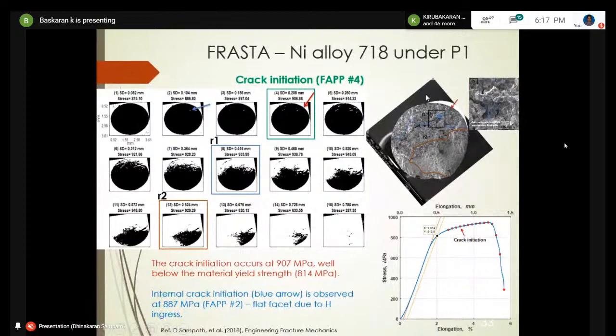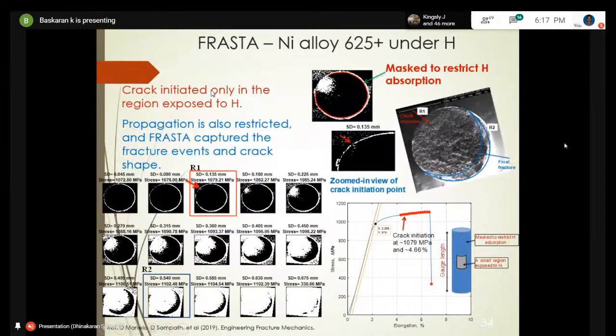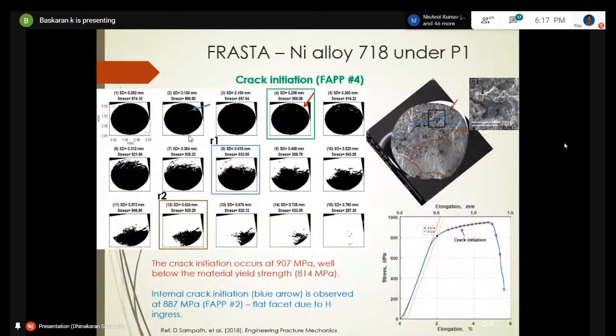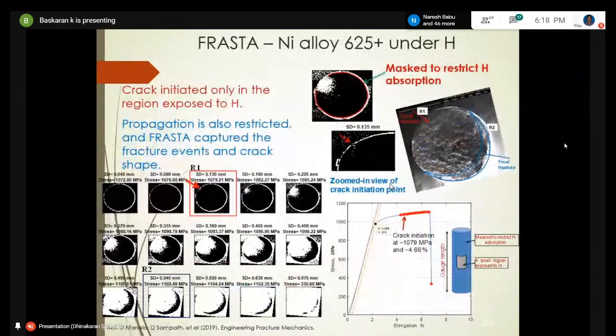And for 718, we did the same exercise and found that the crack initiation occurred after yielding. That means it showed a lot of plasticity before the crack initiated. So that's how we use that technique to differentiate when the crack initiates. It's not a simple tensile test where we expect continuous homogeneous deformation, then necking and then failure. But it is not that way. You have got a crack. That's why people say it's a fracture mechanics test.